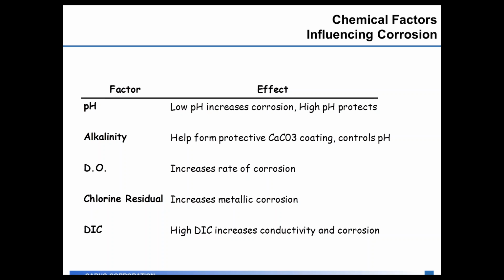In addition to pH, alkalinity is another important factor to measure. Alkalinity helps you form the calcium carbonate coating out in the distribution system, and it also acts as a buffering agent for your water, which helps you keep your pH at a stable level throughout the distribution system. Systems that have low alkalinity typically can see pH swings in the distribution system, where water leaving the plant will be at one pH, and depending on what's going on in the distribution system, it'll either swing higher or lower depending on what type of corrosion byproducts they have in the system.